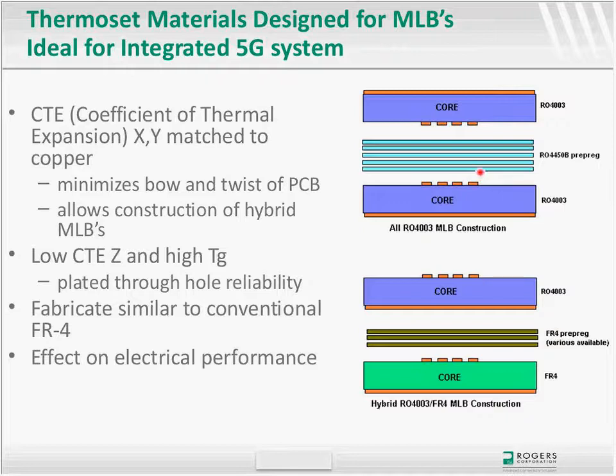In the case of RF materials, there are not that many that have lamination temperature settings similar to that of the traditional FR4. That's usually around 175 degrees Celsius for FR4. So, finding materials that have a low temperature, and Rogers have designed the prepregs to be at 175, then you can really combine various of these prepregs in a single multi-layer process. That is important because it helps reduce the number of lamination steps and helps reduce costs. So lamination temperature is important when selecting the bond plies for these materials.